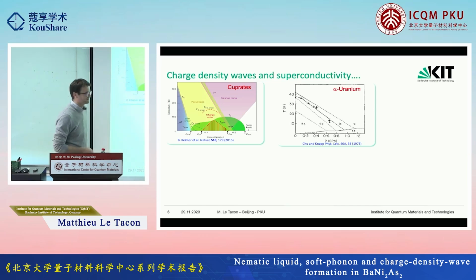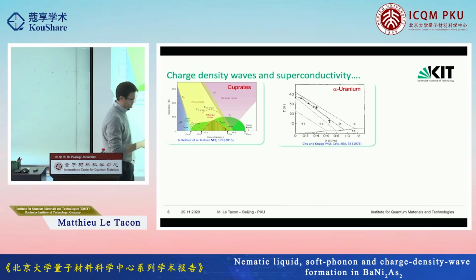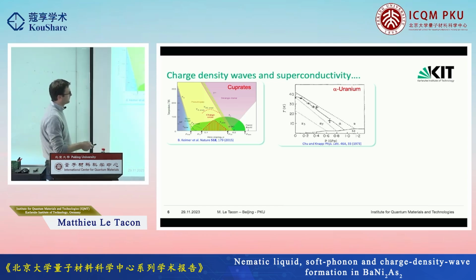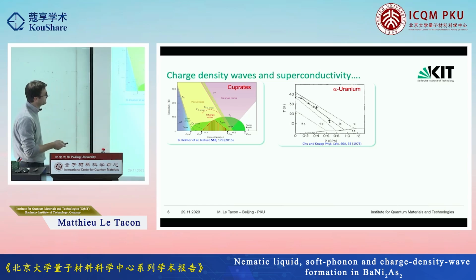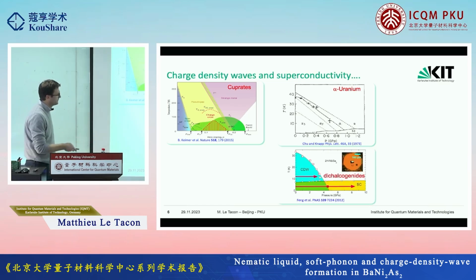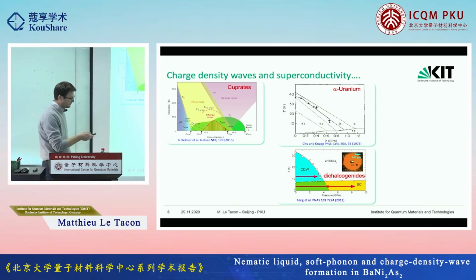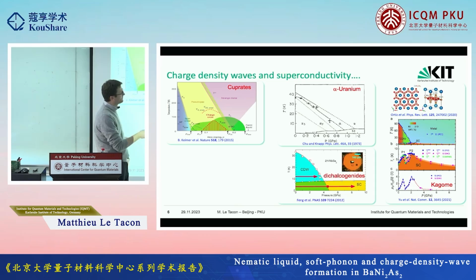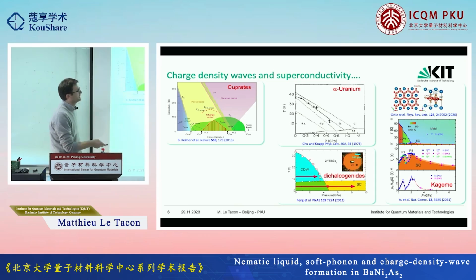Well, that's uranium. So just pure uranium as an elemental compound actually also has a superconducting dome and a charge density wave instability. And I guess what I'm trying to show here is that there are many compounds, so the dichalcogenides, which also have this charge density wave and this kind of superconducting phase at low temperature, and the more recently discovered and widely studied Kagome materials, which have this charge density wave which decreases with pressure and this double dome.